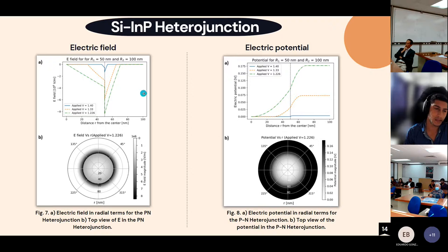It's important to say that the electric field is not continuous at the limit between the two materials. This fact is due to the difference between the dielectric constants of the semiconductors P and N. And figure 7b shows a top view of the electric field in the PN heterojunction for the applied voltage equal to 1.226 volts. For the electric potential, in figure number 8, we get a potential distribution that is